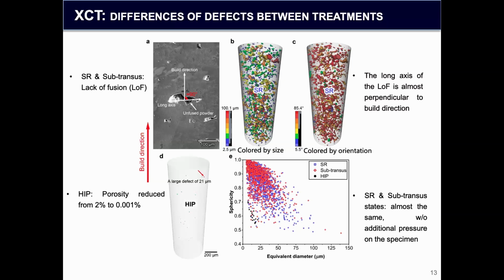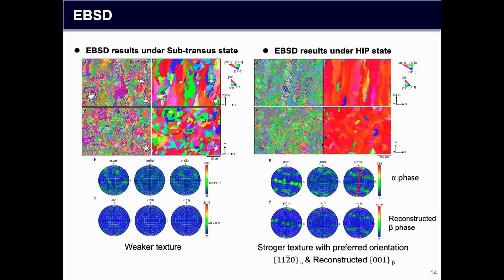And after HIP, the porosity is reduced from 2% to a very small value. And we can also see the SR and sub-transus states have almost the same morphology of the defects, because both of them are without additional pressure on the specimen. I won't go into the detail of the EBSD, but we can find a weaker texture for the sub-transus states and a strong texture for the HIP state.